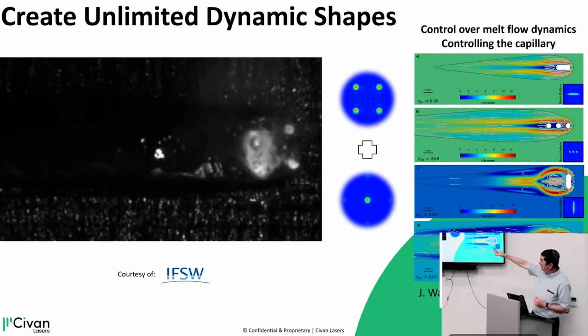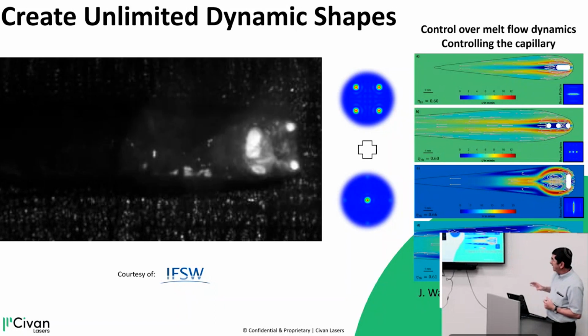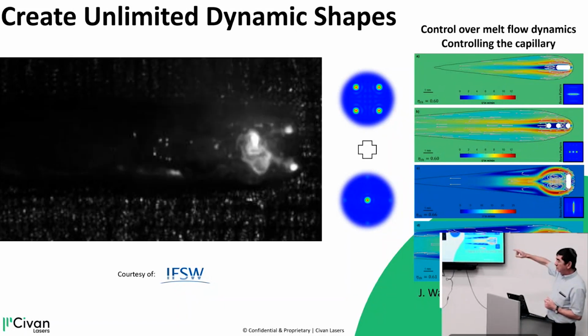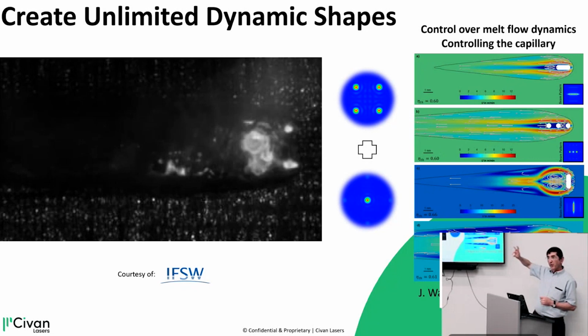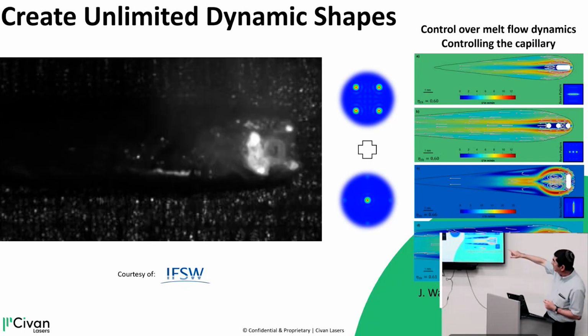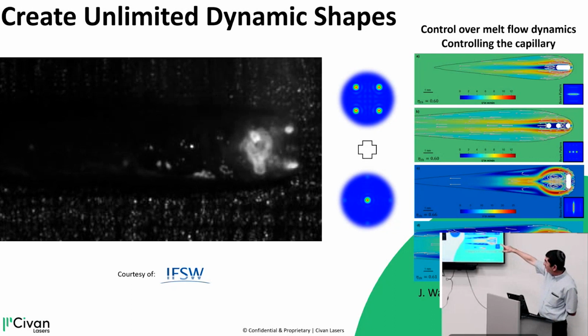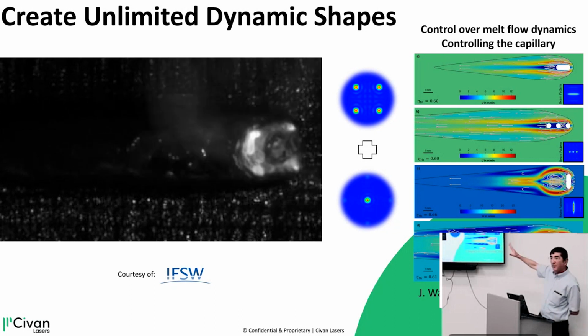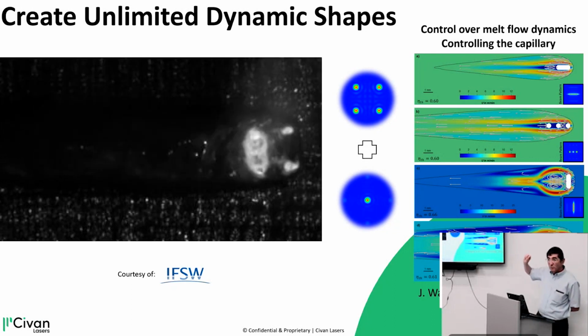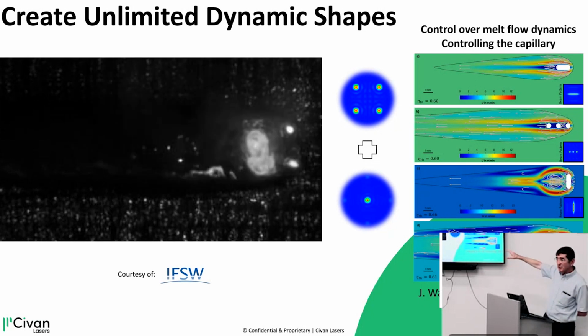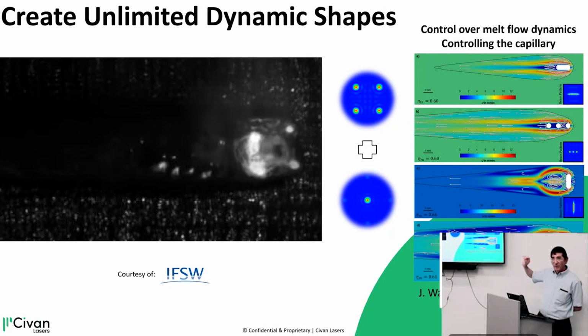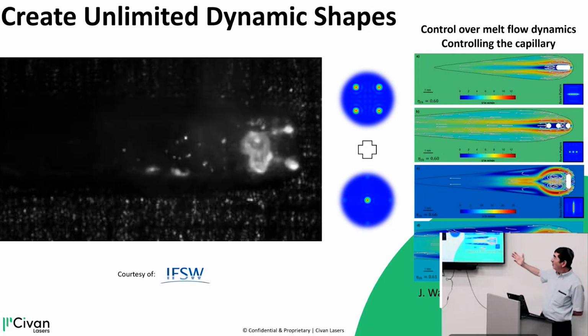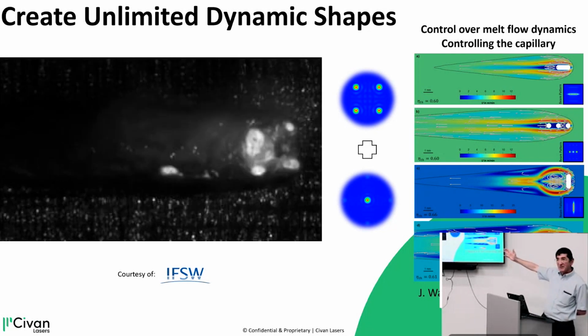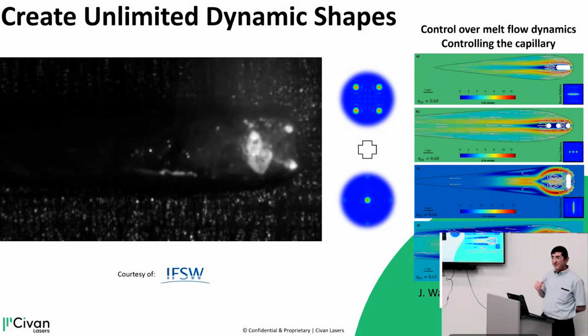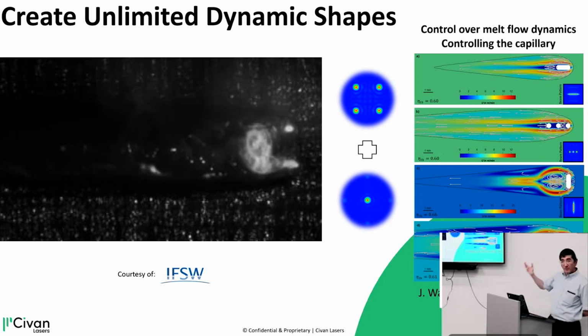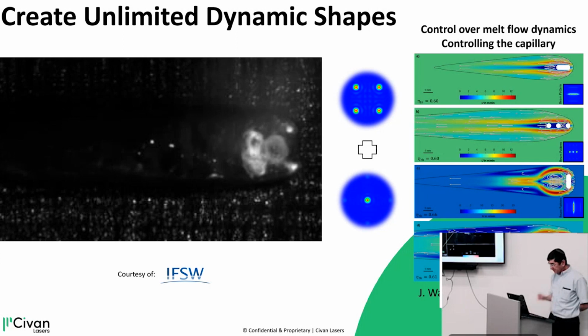And on the left, you see the fast camera where we switch between 2 shapes. On the top, you see the shape with 4 points, and in the center, you see a shape of 1 point. And you see in the camera the 4 points, and once in a while, we create a point in the center that creates these waves, okay? So this is just to illustrate that we actually create waves, motion of liquid metal inside the melt pool, okay? And this is very important for many processes. I'll show a few of them.